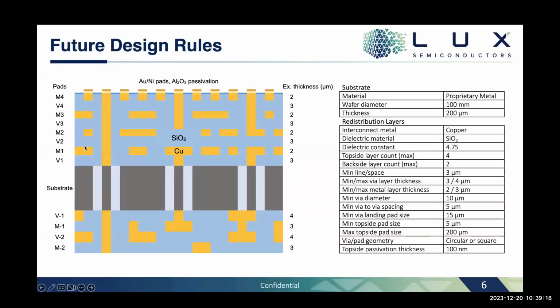But right now we're planarizing every single layer. So if we can get, like we show here, 3 micron line space resolution, and we're pushing that down to 2. And for RF, that really low surface roughness and high fidelity that you get when you planarize each layer is really valuable as you move up to higher and higher frequencies. So the RDL will reduce cost, but it might sacrifice a little bit on those areas. And so it'll be just application dependent.